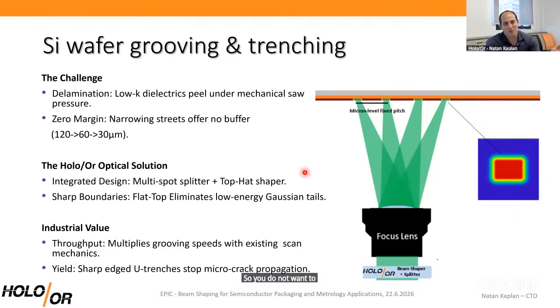So you need to shape the beam into a flat top beam, a small flat top beam, requiring very precise shaping, which is usually achievable mostly by diffractive optics, because to shape very small angles, few diffraction limits, it's not really practical in most other methods. And of course, you want more throughput. So you do not want to just groove one. You can groove them with very precise separations, and this can all be done by a single diffractive optical element. It can combine the beam shaping and the beam splitting functions into a single element.